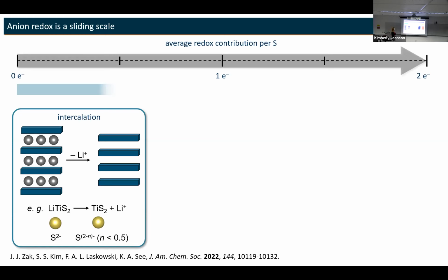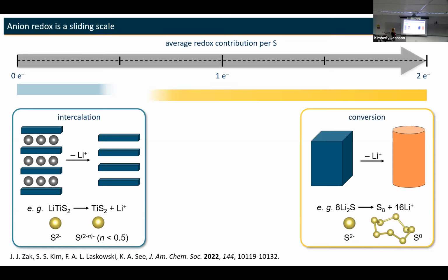So this is sulfur chemistry, if you're familiar with this, lithium-sulfur batteries. So this is lithium sulfide converting to sulfur. Those phases are very, very different. So you get massive volume changes. The mechanism is very complicated and it's not very reversible, but the capacity is extremely high.